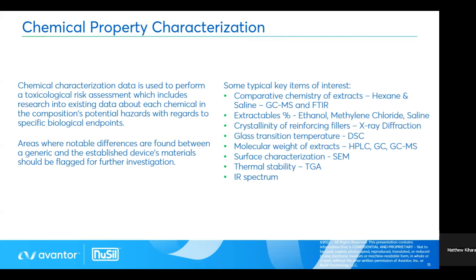Crystallinity of the reinforcing fillers using X-ray diffraction. Glass transition temperature using DSC. Molecular weight of the extractables using HPLC, GC, and GCMS, surface characterization using a scanning electron microscope, thermal stability using TGA, and an IR spectrum. These all also have ASTM standards, ISO standards, and USP standards that can be used as guidelines. Next slide, please.